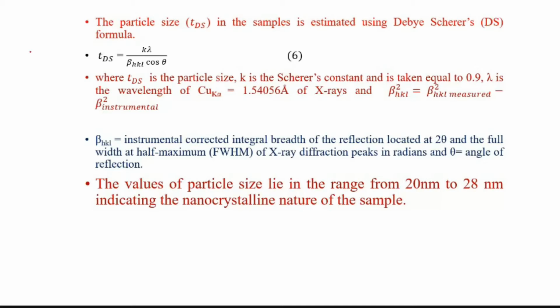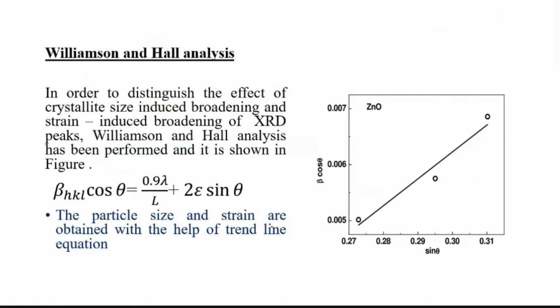So what will be the particle size of the materials? We are using this Debye-Scherrer formula, where T, the thickness, is the particle size, K is the shape constant, lambda is the wavelength, and beta is the full width at half maximum of the X-ray diffraction peaks. So this is the formula by which we can get the particle size of our material. What we are observing here is that the range of our particle size is from 20 nanometer to 28 nanometer, and that is indicating the nanocrystalline nature of the sample.